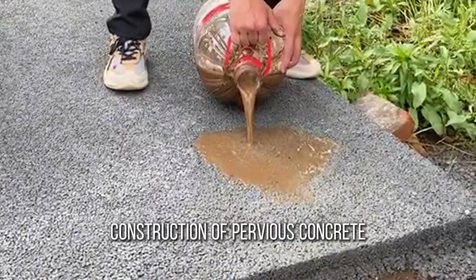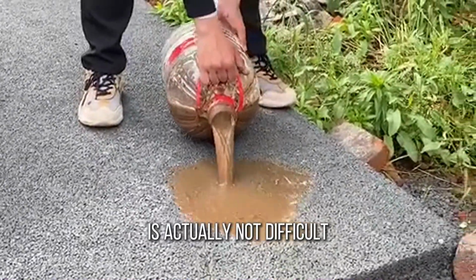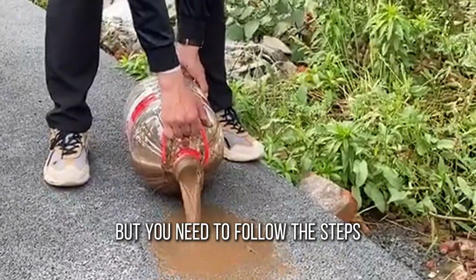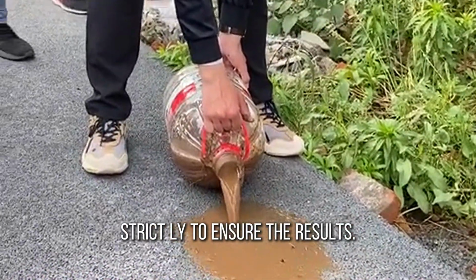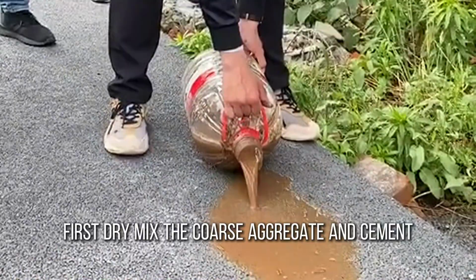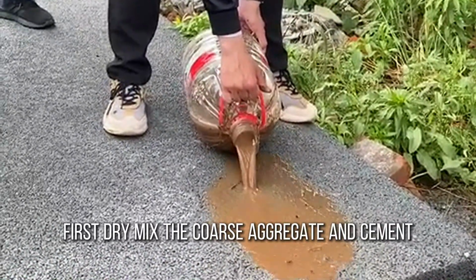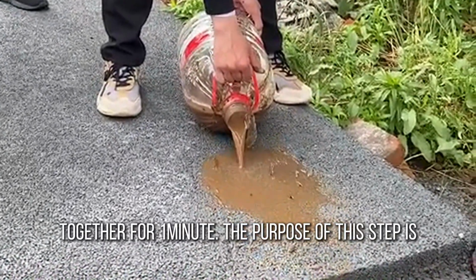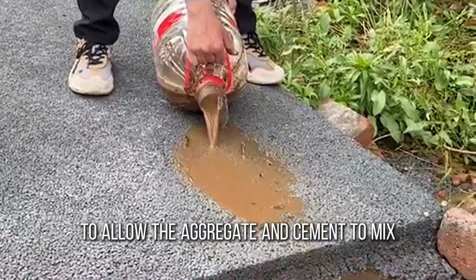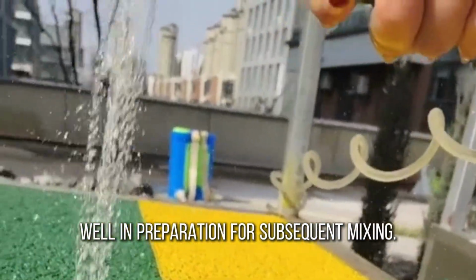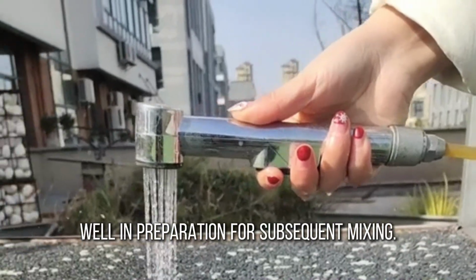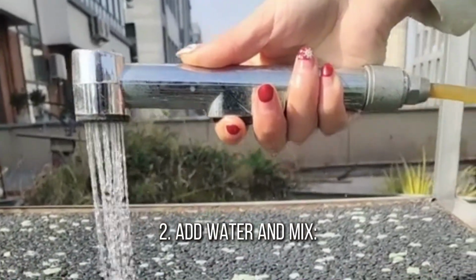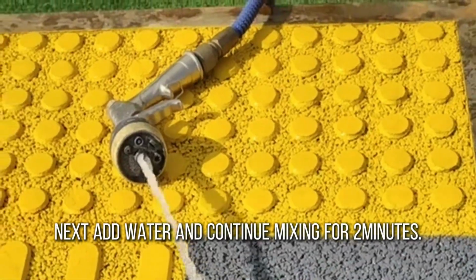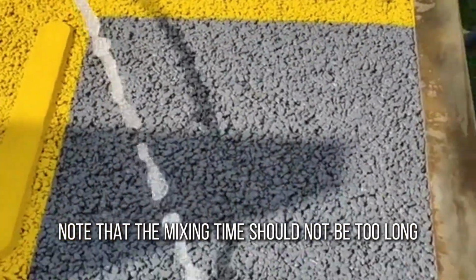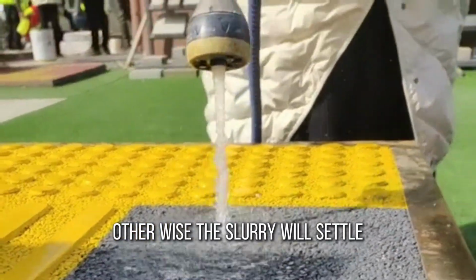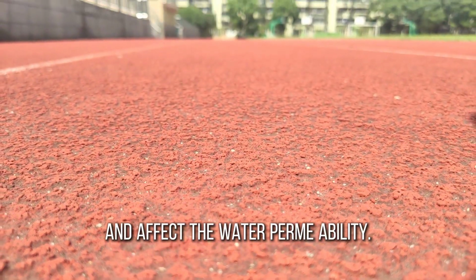The construction of pervious concrete is actually not difficult, but you need to follow the steps strictly to ensure the results. 1. Dry mix. First, dry mix the coarse aggregate and cement together for 1 minute. The purpose of this step is to allow the aggregate and cement to mix well in preparation for subsequent mixing. 2. Add water and mix. Next, add water and continue mixing for 2 minutes. Note that the mixing time should not be too long, otherwise the slurry will settle and affect the water permeability.